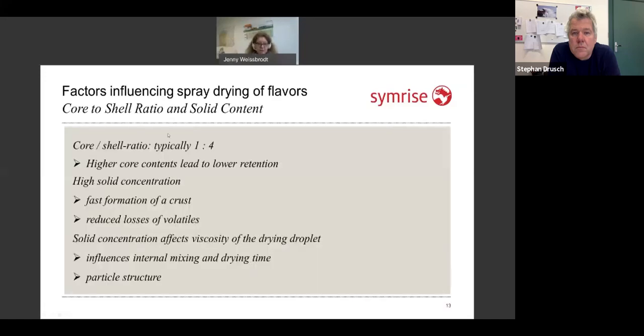Coming to the core to shell ratio and the solid content. Normally in spray drying, you very often have this ratio of 1 part active to 4 parts of solids or carrier material. Of course, you can change this relation however you need it, but you have to bear in mind that a higher core content or active content normally leads to a lower retention, because you just have less material to entrap it. A very high solid content leads to a very fast formation of a crust or of a membrane on the surface of your drying droplet, and this will reduce losses of your volatiles.